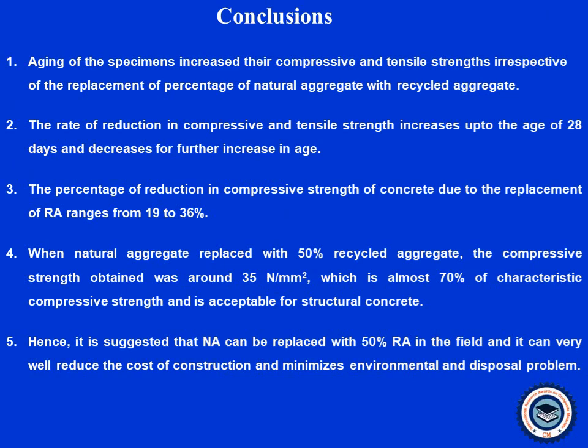So finally we conclude like this: the aging of the specimen increased the compressive and the tensile strength irrespective of the replacement percentage of natural aggregate with recycled aggregate. The rate of reduction in the compressive and tensile strength increases up to the age of 28 days and decreases for further increase in the age. The percentage of reduction in compressive strength of concrete due to replacement of recycled aggregate ranges from 19 to 36%. When natural aggregate is replaced with 50% recycled aggregate, the compressive strength obtained was around 35 Newton per mm square, which is almost 70% of the characteristic compressive strength and is acceptable for structural concrete.